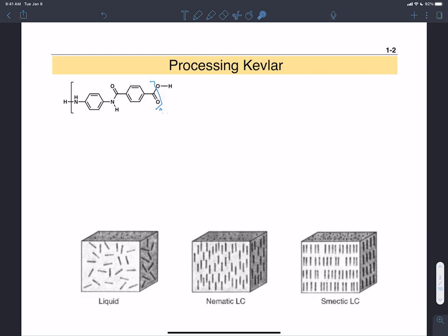And frequently, I would suppose that for other systems that also lack these types of hydrogen bonding motifs, their intermolecular interactions are also considerably higher. I still think there could be an entropic effect of having this much ordered solvent around a polymer chain with very few degrees of freedom, which probably makes it more challenging for solvation as well. So there's a number of factors that can go into this. Frequently, if you have a rigid polymer and you want to make it dissolve a little better, you add on side chains that will increase its solubility. And that's something we'll see here in a few slides on Kevlar derivatives.